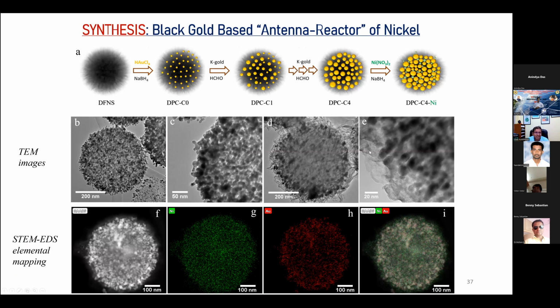This is how we synthesize the material. We prepare the black gold, load it with nickel salt, reduce it by sodium borohydride, followed by a second reduction, and we got small nickel nanoparticles. Although we were not able to see the nickel nanoparticle in normal imaging because of the similar contrast between gold and nickel, when we did the elemental mapping, we were able to clearly see that nickel is uniformly loaded onto the black gold.